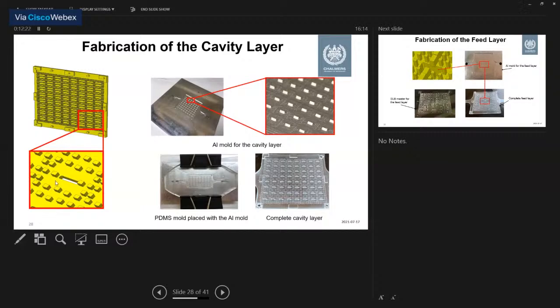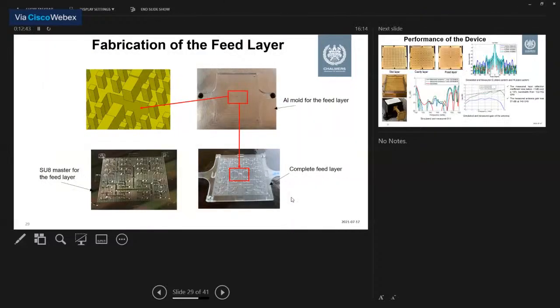So the challenge of this cavity layer is it has this hole. To get this hole, we design the aluminium mold in a way that it has some pins. And then when we inject the elastomer, the pin actually creates this opening. And here you can see a complete cavity layer. In a similar way, we fabricate the feed layer. But for the feed layer, we have only one pin in the middle, which creates this opening for the transition.